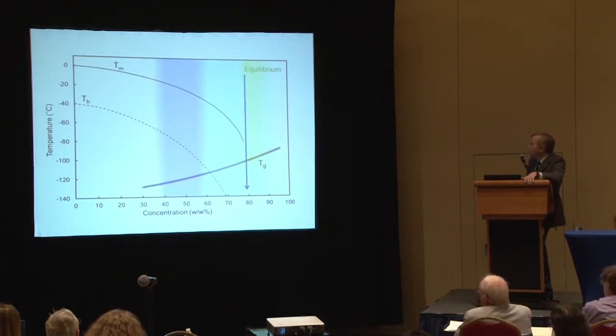Equilibrium vitrification was used a few years ago by Kevin Brockbank and his group to cryopreserve heart valves. It was advantageous in that application because you could store and ship heart valves at a dry ice temperature of minus 80 degrees and not have to worry about ice formation.